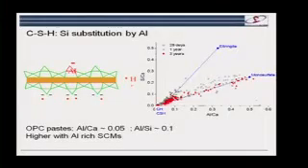If we look at these kinds of analyses taken in the scanning electron microscope of cement paste, I'll explain how we do these plots later. But you can see this cluster of analyses here. These represent the calcium silicate hydrate, and they have a quite definite amount of alumina attached, typically an alumina to calcium ratio of about 0.05. And interestingly, all Portland cement without additions seems to have roughly the same amount of alumina in.